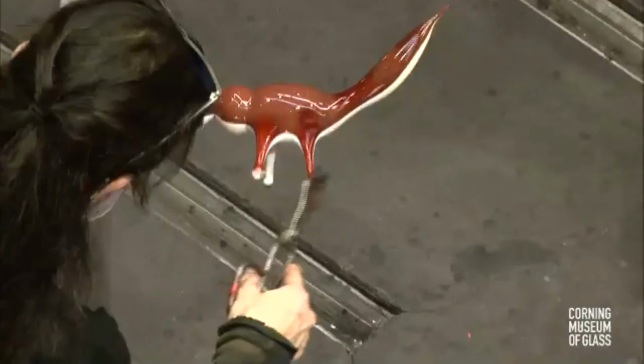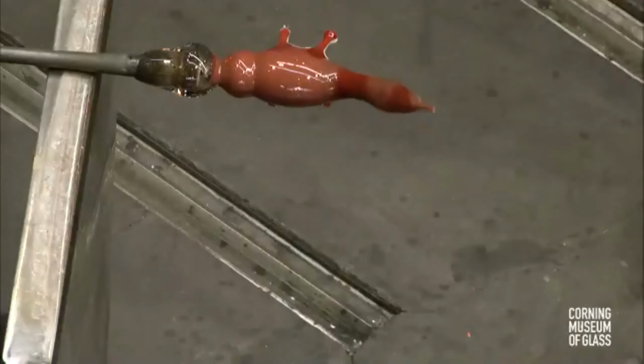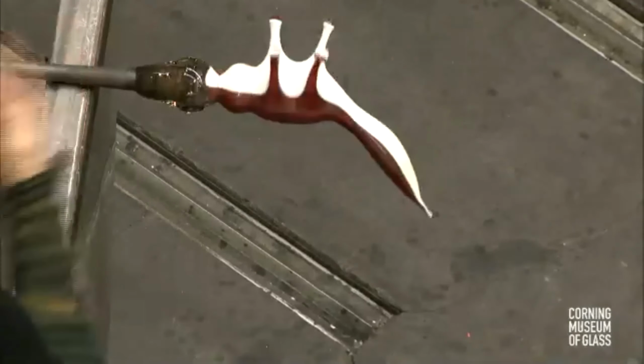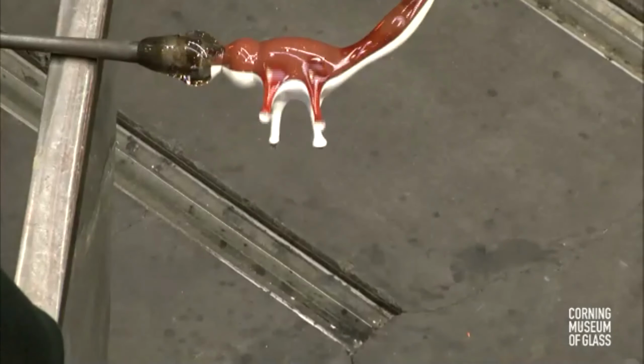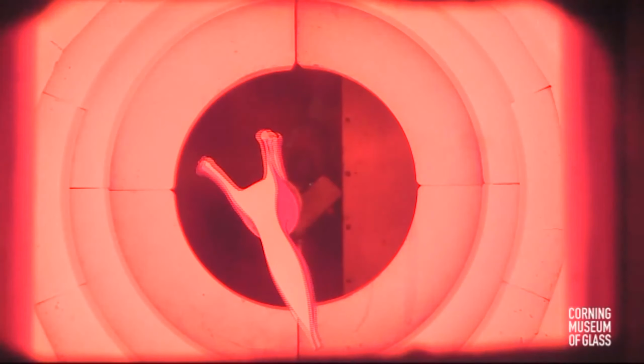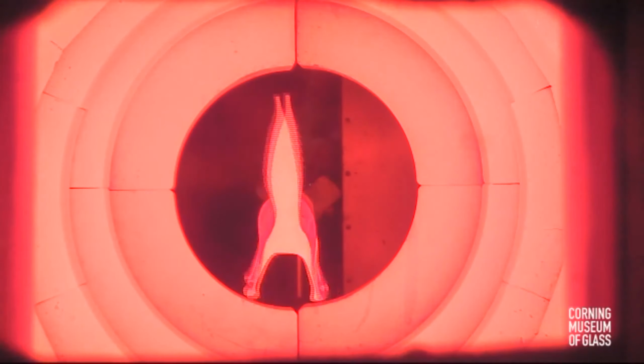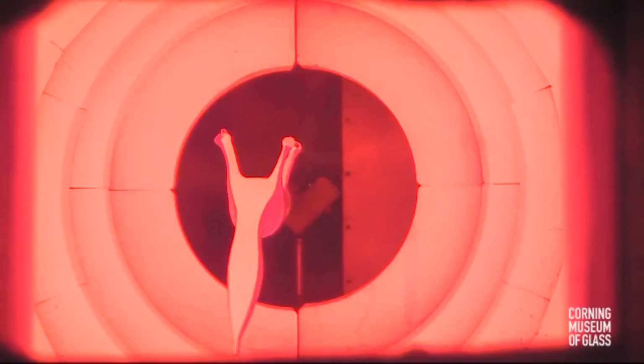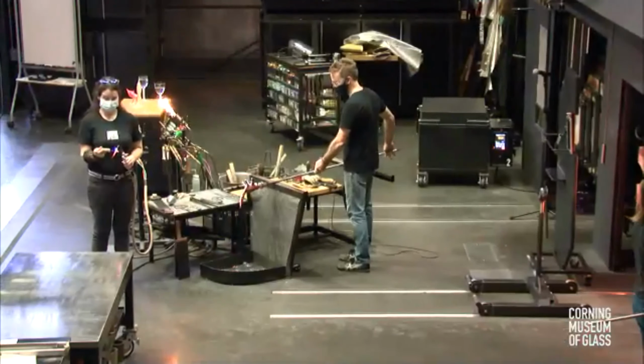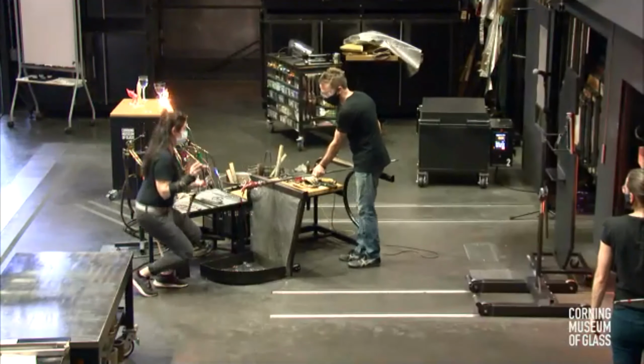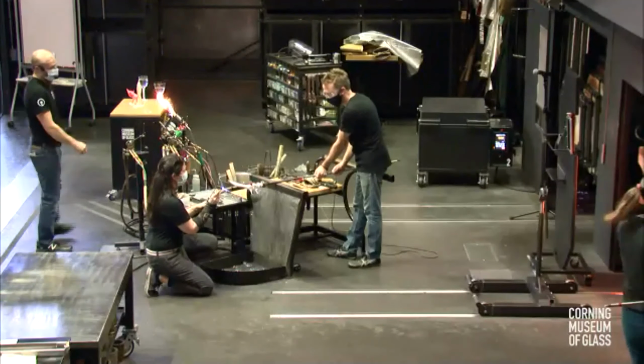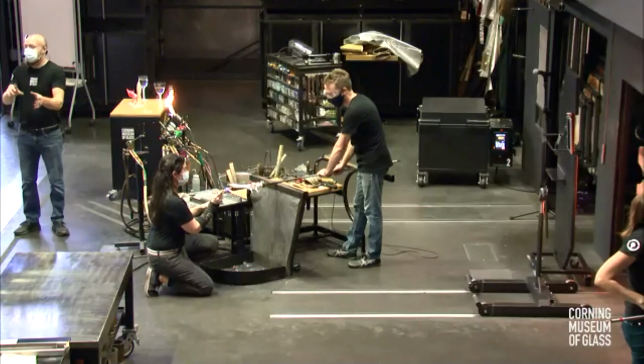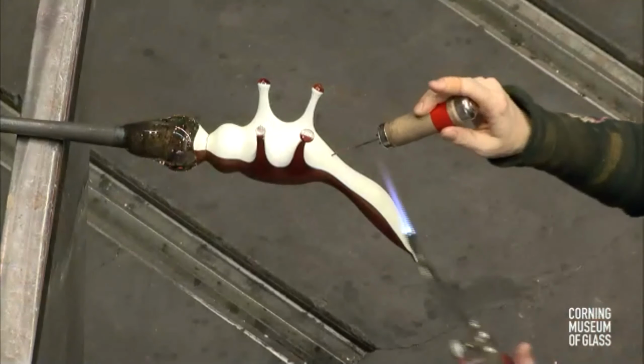Well, the rest of the vessel, we know it's above about 1,000 degrees. And we know that because if it's cooled below 1,000 degrees, it'll actually shatter, it'll crack and break while we're making it. In fact, while they're using the torch, the one spot they're torching can be so hot that it's molten and malleable. They're stretching and pulling it. Let's see, one of the little legs there, if it gets too cold, it could crack and break. And that would be a bad thing. So what we're going to do now is make sure that the temperature is just right. And that flashing process maintains the temperature at about 1,000 degrees.